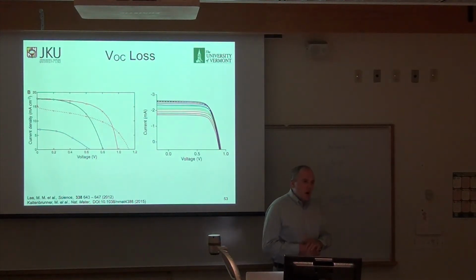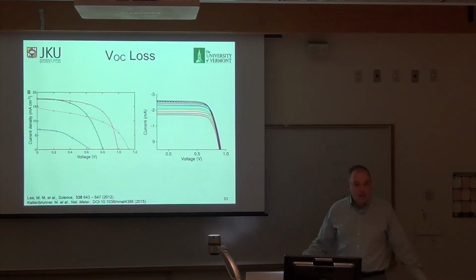We think that by enabling this film forming layer on the PEDOT:PSS, we were able to make large area electrodes, or large area solar cells, or relatively large area solar cells, repeatedly on very flexible substrates, and use them for the demonstrations that we wanted to. But there's a sacrifice, and that is the VOC. In our devices, in all of our devices, the VOC was under 1 volt.